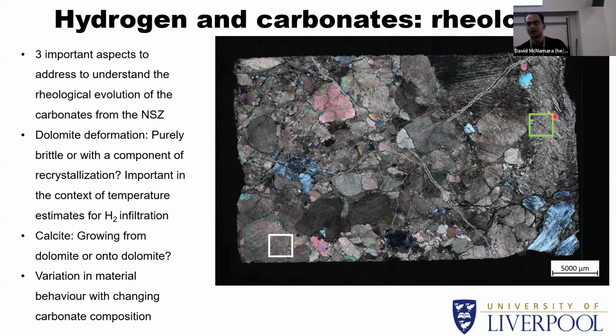So the first bit is, how do we deform the dolomite? Is it entirely brittle, or is there a component of recrystallization? Now, dolomite is notoriously difficult to recrystallize because it likes to form twins, it likes to break apart, but it's really sluggish when it comes to the motion of dislocations, and it needs high temperatures. So if this fine-grained bit here were to form by recrystallization of dolomite, you would need very high temperatures. Temperatures that would possibly then promote the thermal degradation of carbonate, and then the hydrogen story becomes sort of unnecessary.